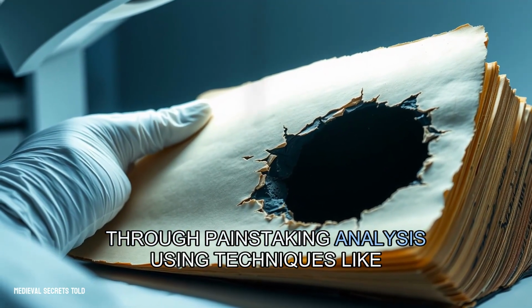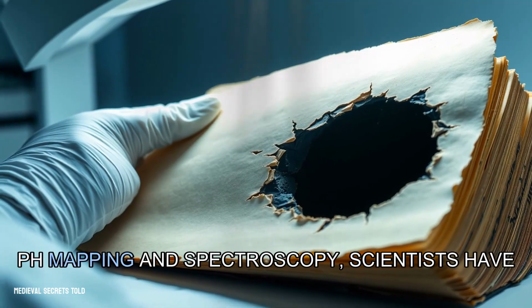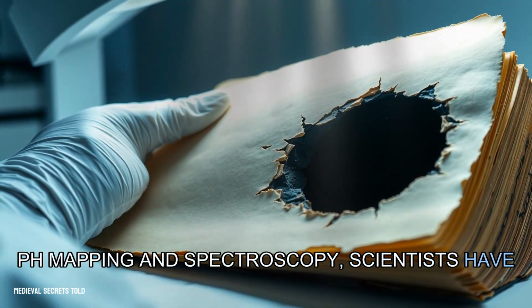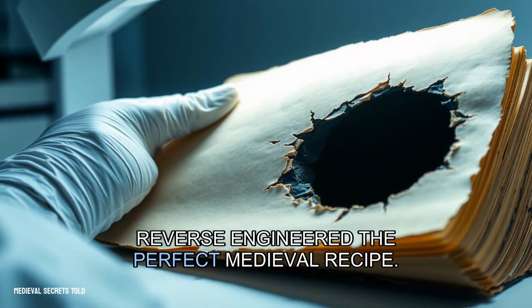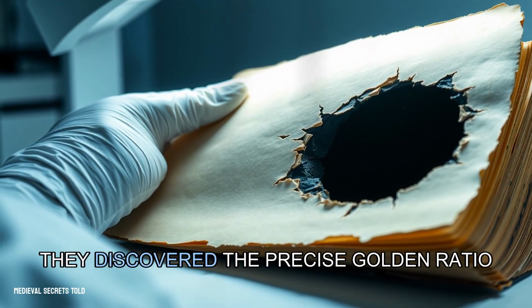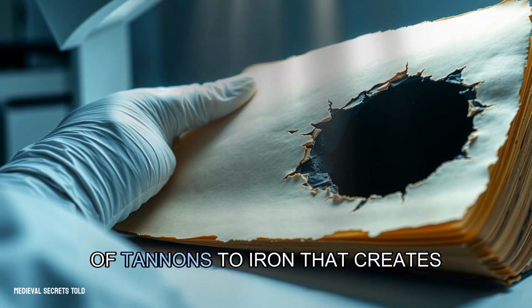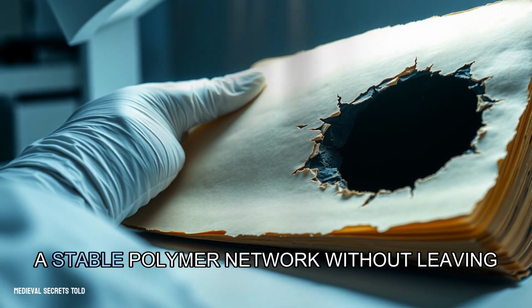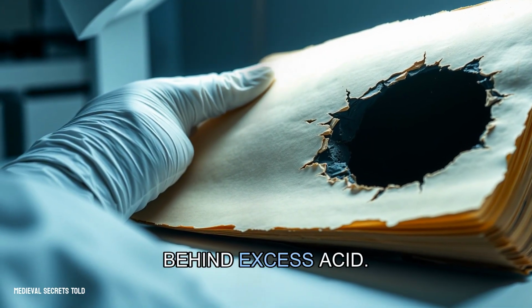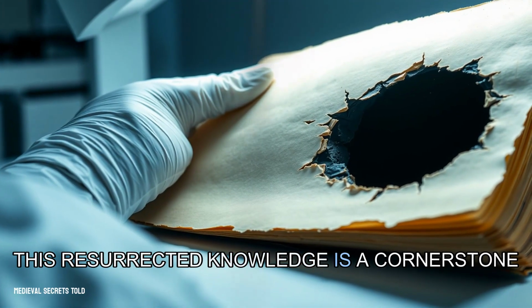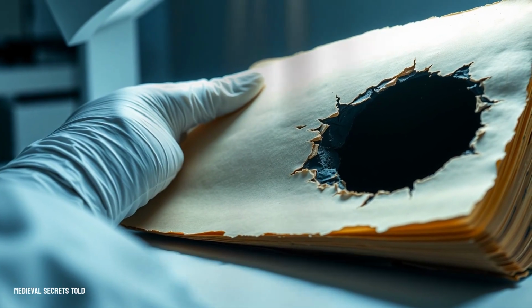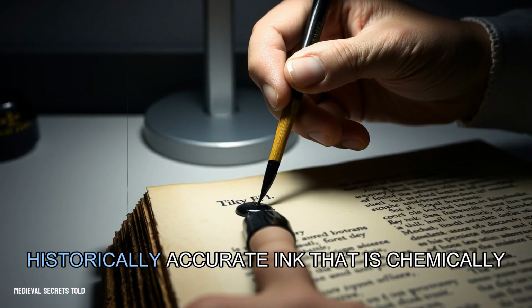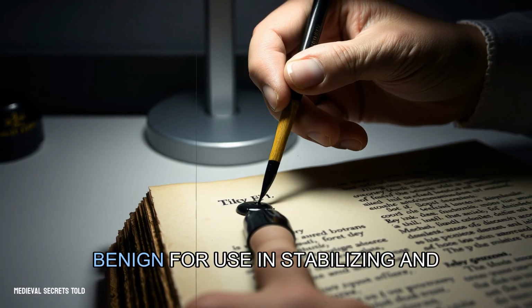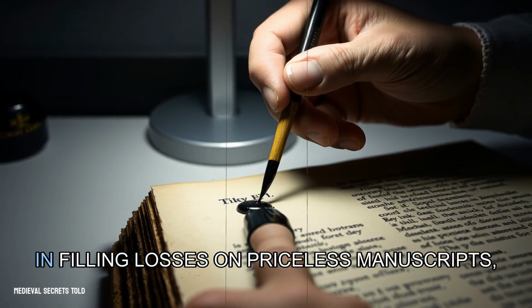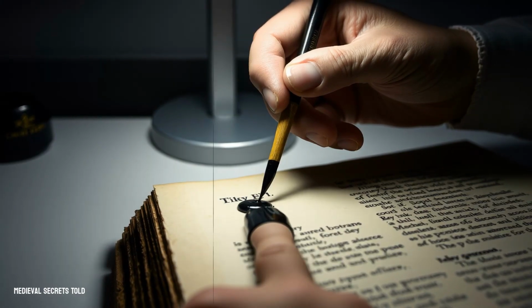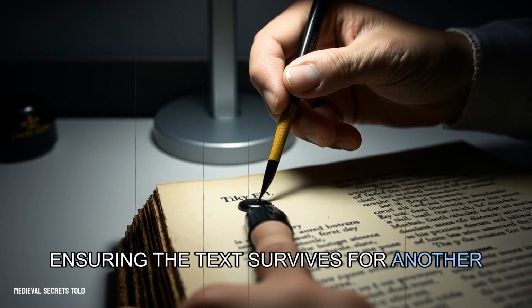Through painstaking analysis using techniques like pH mapping and spectroscopy, scientists have reverse-engineered the perfect medieval recipe. They discovered the precise golden ratio of tannins to iron that creates a stable polymer network without leaving behind excess acid. This resurrected knowledge is a cornerstone of modern conservation. It allows experts to mix a historically accurate ink that is chemically benign for use in stabilizing and in-filling losses on priceless manuscripts, ensuring the text survives for another millennium.